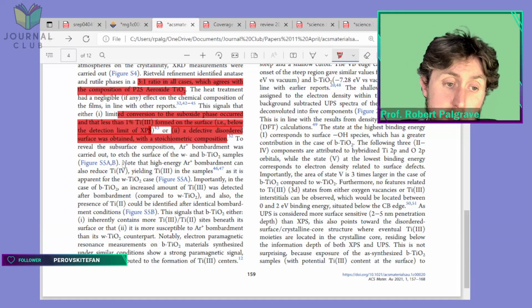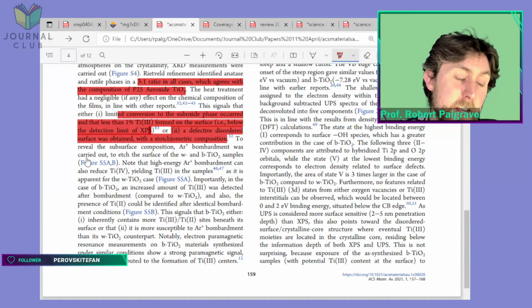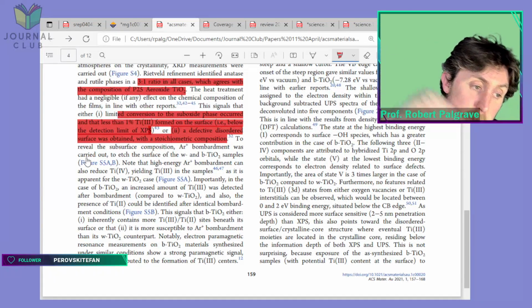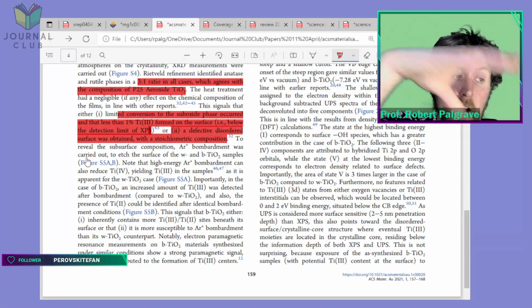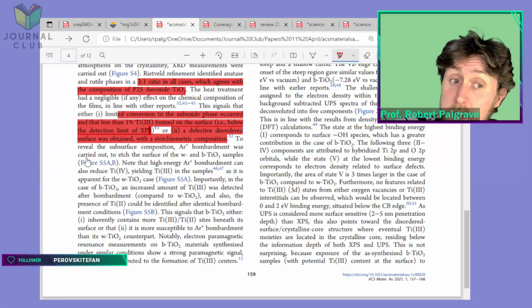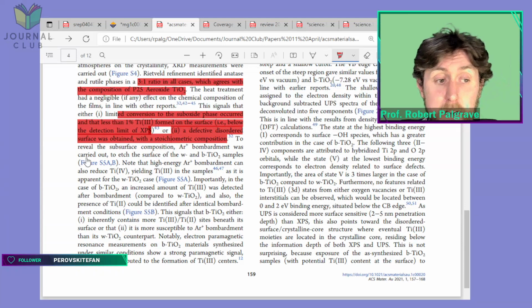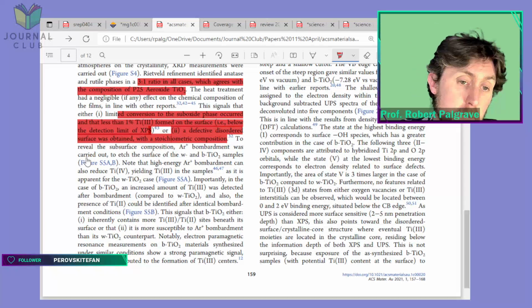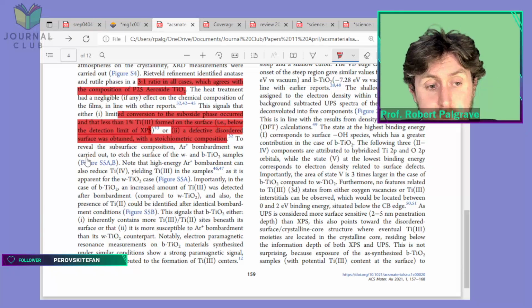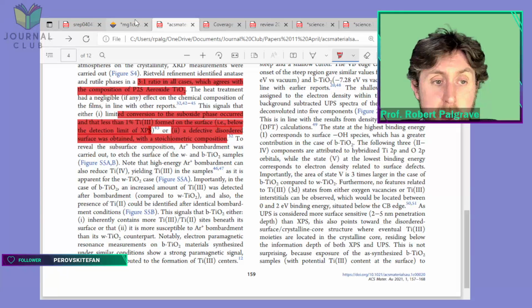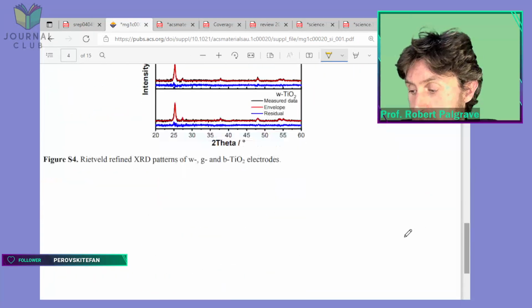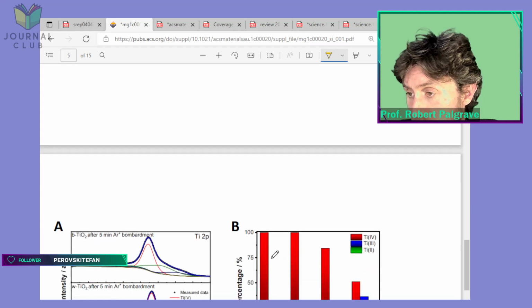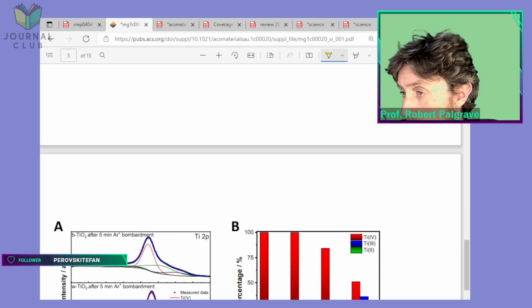So they're talking about XPS. One thing you can do in XPS is use argon ion bombardment to sputter away, to physically remove the surface and have a look at what's underneath. That's called depth profiling, or argon ion sputtering, argon bombardment as they call it here. Very, very widely used. So let's have a look at what happens here.